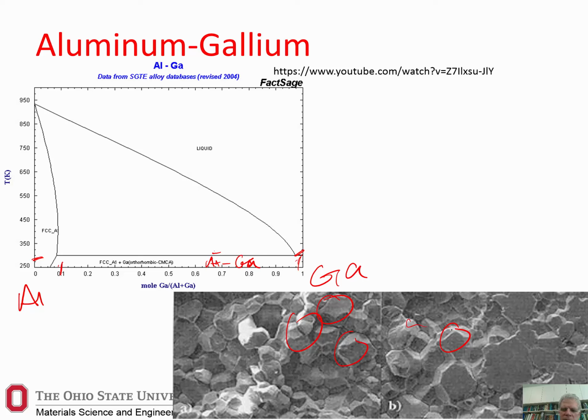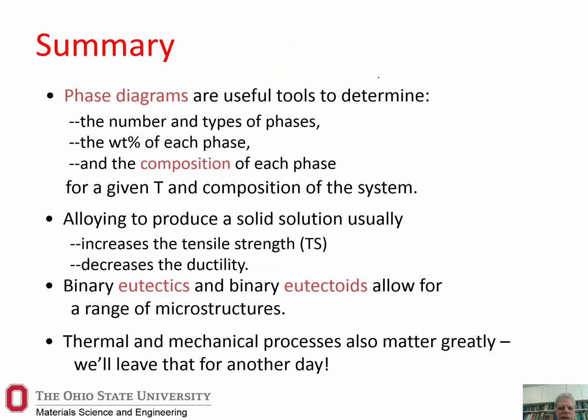This is called liquid metal embrittlement. But it's also kind of a cool thing in that it opens up a structure and allows you to see how those crystals pack together. So these are all individual crystals, kind of harkening back to what the material structure looks like. And again, you can explain that this small amount of phase segregates, a little bit of gallium wants to still be liquid, finds its morphology on the grain boundaries. It can be an embrittler. And there are some neat YouTube videos on what gallium will do to aluminum. It has been used, we think, for nefarious purposes in the past.